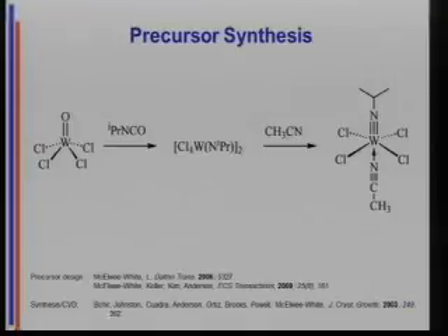I can run H2 in my carrier gas, and I can remove these 4 chlorides as HCl. HCl is better for the silicon wafer than HF. It's a problem with process equipment, and we're going to come back to that. I'll get rid of it by the end of the talk. And then all I have to do is break 1 nitrogen-carbon bond, and I have a building block for tungsten nitride thin films. Looks good, right?